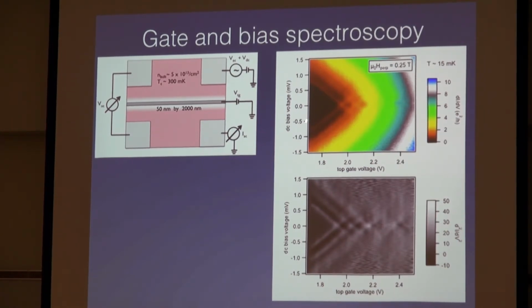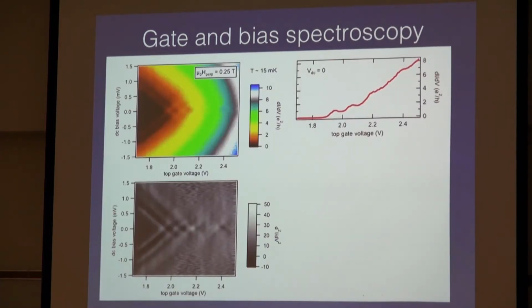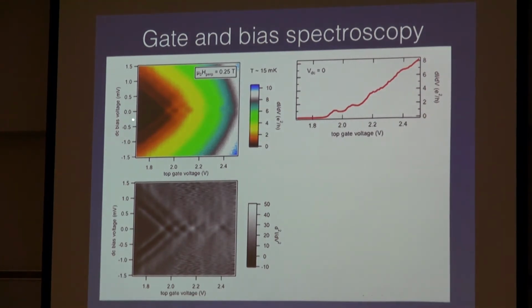And if you look at it, when the gate voltage is small, so say 0 to 1.6, 1.7 volts, you don't get any conduction, basically because the strontium titanate underneath this is still insulating. But as you turn up the voltage and start to bring in electrons into the system, you start to see conduction. And if you take a look at that conduction, so this is just a slice right here through 0 applied bias voltage, you see steps in conductance. And those steps occur at 1 and 2 e²/h.